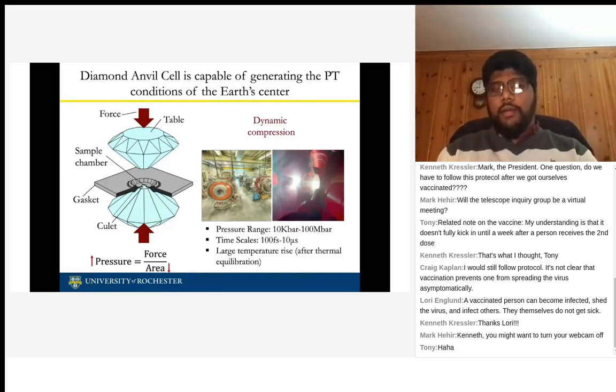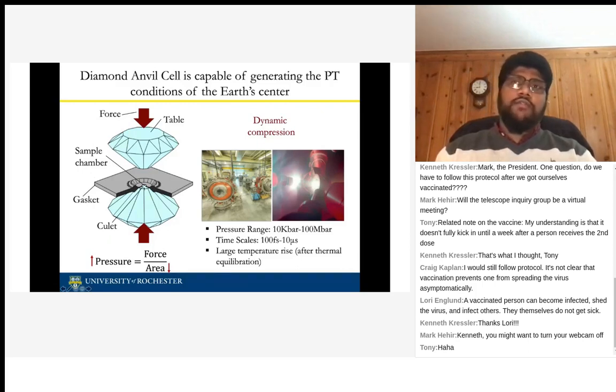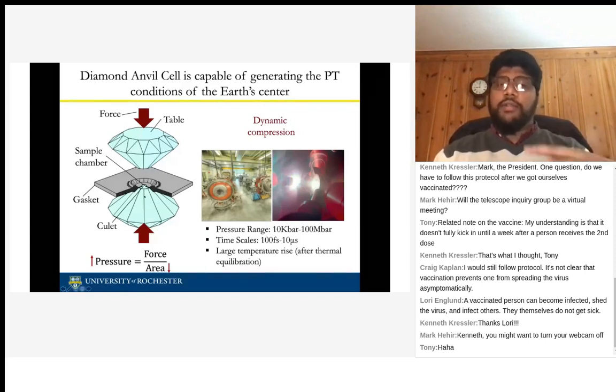The diamond anvil cell, on the other hand, the problem is that your sample size is going to be really small depending on the pressure you want to reach. For example, if you want to reach 500 gigapascal, you need a culet size of about 30 micron in diameter. So it's really small samples compared to dynamic compression. But these two go together. So you really use both techniques, depending on the PT condition that you want to study. So I use both of these techniques.